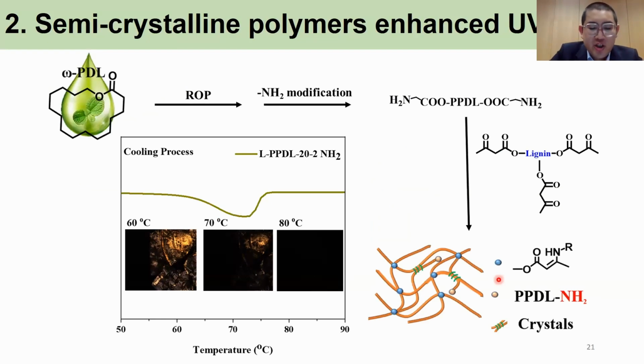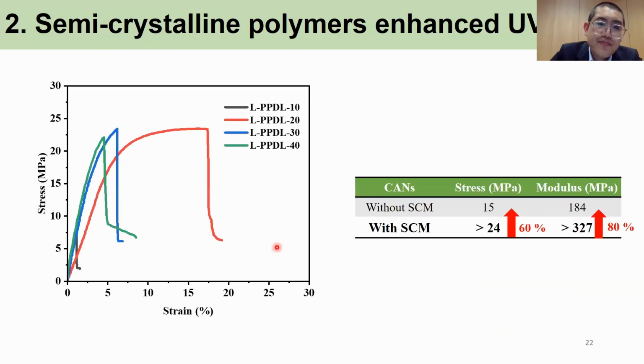The second enhancement measure we chose is using a semi-crystalline polymer. PPDL material is a semi-crystalline polymer. We made this polymer from the monomer PDL. We use ring opening reaction followed by amine modification, then cross-link with the modified lignin to prepare the CANs material. From the DSC results and the optical microscopy, we can find these beautiful crystals. And these crystals gradually melt as the temperature increases. These crystals significantly improve the mechanical properties of the CANs material, with stress at break increasing by 60% and the Young's modulus increasing by 80%.